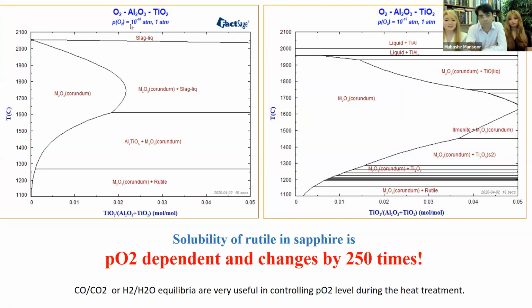But dissolving rutile in sapphire is dependent on the oxygen partial pressure, and therefore it changes by even more than 250 times. Therefore, it's a very, very efficient process. So these are the diagrams that I mentioned that have not been published yet, and you're the first to actually look at them. We did all sorts of different thermodynamic calculations, and we realized that if you reduce the oxygen inside the furnace, there is a very fundamental change in the material, in the sapphire. And that fundamental change increases the amount of rutile that you can dissolve. It increases it by 250 times.